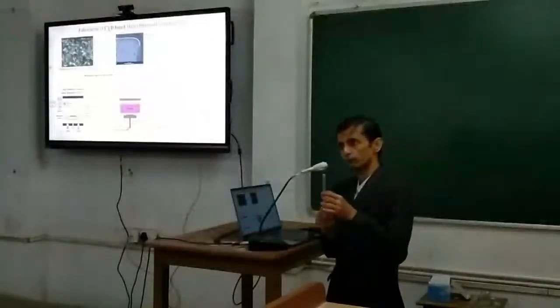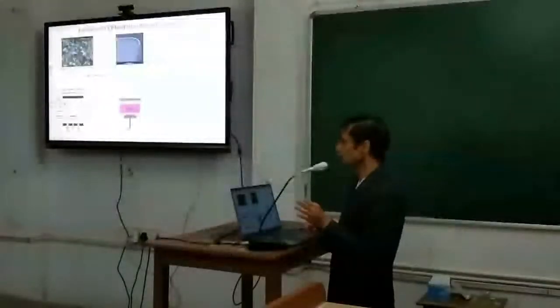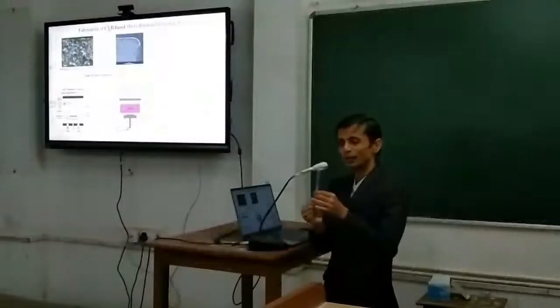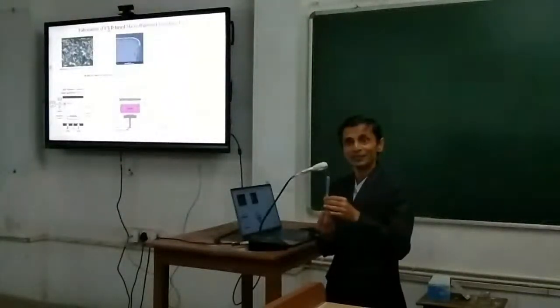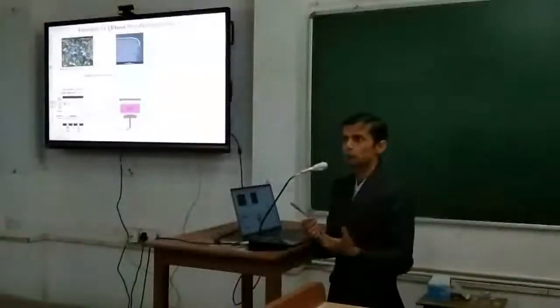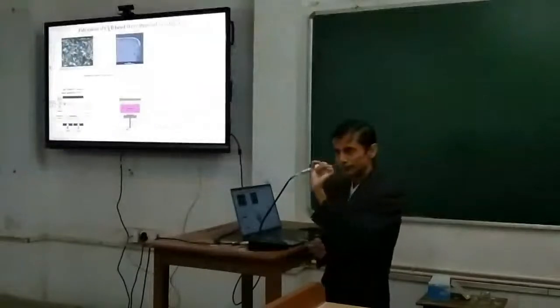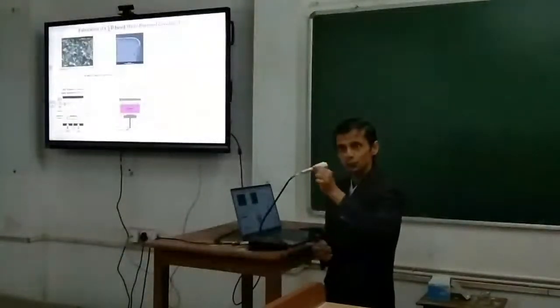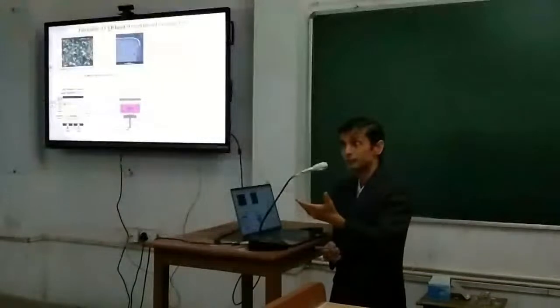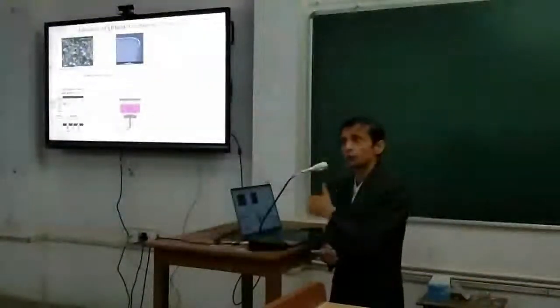But here what we do, we take the same diamond CVD coating, thick coating, might be 20 micron, 30 micron coating. Then we ablate the coating with the laser to create the geometry of the tool. So what will happen now, the same coating will be there with the definitive tool geometry. Is it not a better choice? Because otherwise your diamond particles, CVD particles don't have any kind of definitive tool geometry. But in this particular case, you are texturing a coating, and you are texturing in such a way that every segment of the cut portion becomes a cutting tool. Okay, so that will be having a definitive tool geometry. Now with that, machining is much better, grinding is much better, because now that question of high specific energy is not coming into the picture at all.